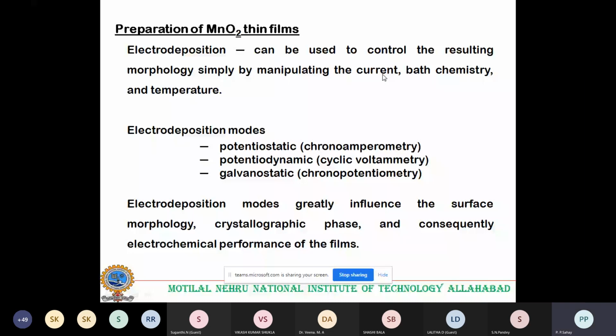Now in the electrodeposition, there are three modes by which the film can be deposited. The one we call the potentiostatic mode. Here, the voltage on the substrate is kept constant. In the potentiodynamic mode, we use cyclic voltammetry, that is, a scan rate. In the case of the galvanostatic mode, you fix the current.